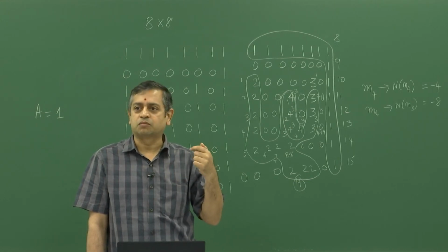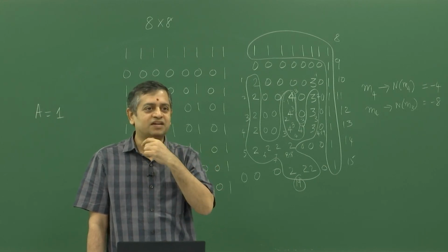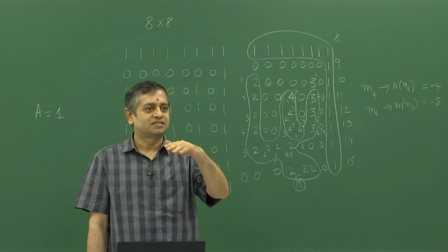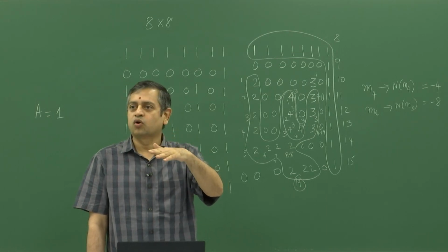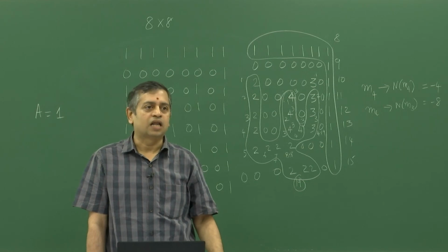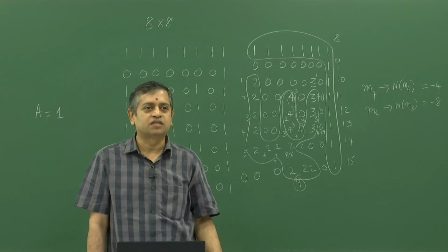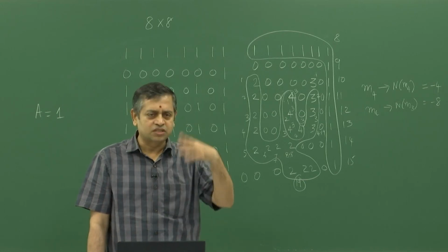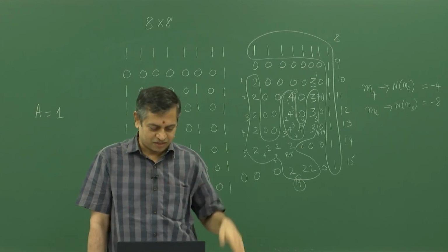I do not know if you know about this Mayan gold, or Tumbaga gold, as they call it. The Spanish went to South America and got lots of gold, but it is pure gold only on the surface, a micron or so. That is because the other atom is leached out on the surface, so it is pure gold there, but inside it is basically an alloy. The rest of it is not gold. In this case we found it was copper and gold. So there are many practical problems where percolation is important, and this is a strange example of that.